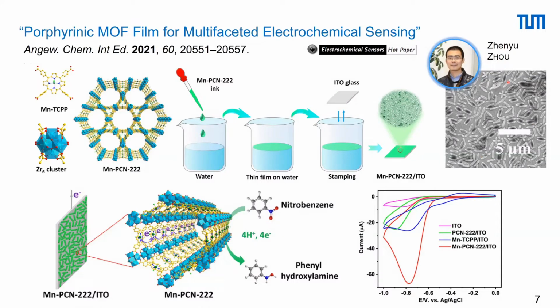And you see here this nice worm-like, rod-like MOF crystallites on the scale of a couple of microns. They are nicely attached to the conductive oxide glass. And this basically gives you the electrode for the voltammetric sensor. So if, for example, nitrobenzene would be the analyte, we would see this characteristic redox potential, or the current when the potential is correct for the oxidation or reduction, depends on what you do, of the nitrobenzene to, in this case, the phenyl hydroxylamine.